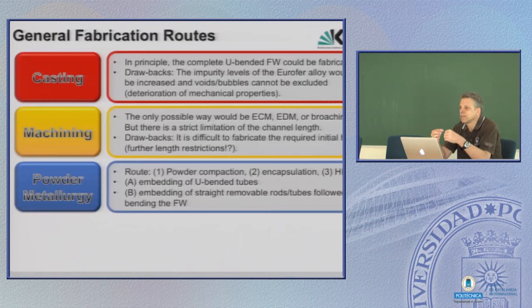One is that we fabricate these long cooling channels in form of pipes, bend them in U-shape, arrange or stack them, and fill them or surround them with powder, and then put everything in a capsule, press it together, and that's it. But, well, the problem is the same as with tungsten. Powder compaction ends in a reduction of the volume, and I doubt it very much that over a length of almost 3 meters, all these tiny distances between the cooling channels would be kept precisely with a distance of 5 millimeters and only 3 millimeters or so to the outer side.